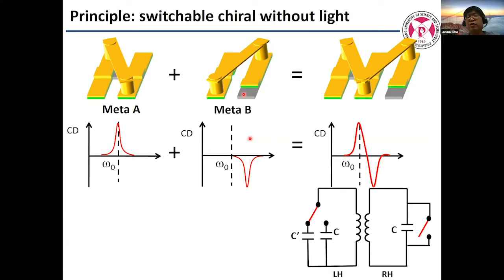And we introduced a little anisotropy. So this part is replaced by silicon, and the other is all gold. In this case, this silicon is a dielectric, so the LC circuit's length becomes shorter, and the resonant frequency moves higher. And here is another silicon, but it has no effect here. So combining these molecules A and B, we can make a positive circular dichroism resonance.